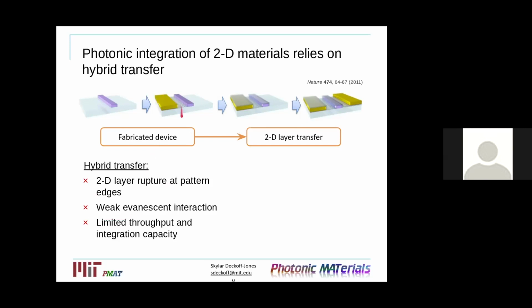For example, as you can imagine, you now are transferring a planar material to a non-planar surface, which can result in stresses and strains and potential ruptures in the 2D material. Additionally, you're limited to the 2D material being on the top of the waveguide, which means you're only going to have weak evanescent interaction. And also, scaling this up for high throughput on wafer scale systems is potentially difficult.